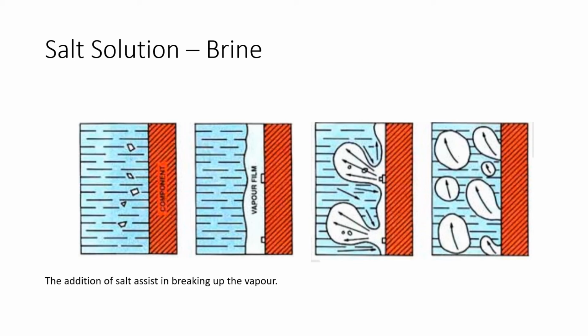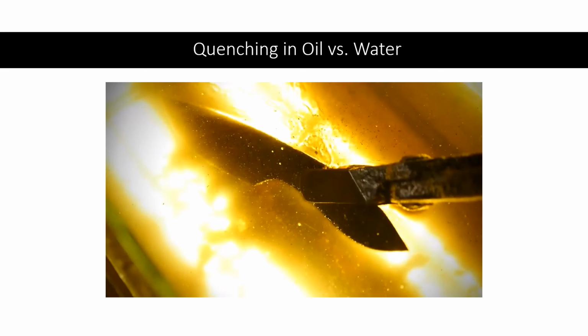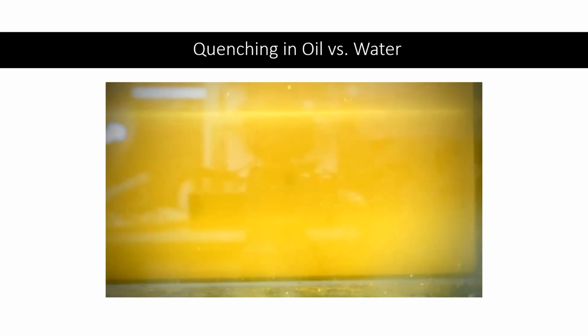This means that a lot more austenite will be transformed to martensite, which is hard in nature compared to ferrite and pearlite microstructure. On the other hand, why does quenching in oil exhibit the slowest cooling rate between the three mediums? The quenching velocity of oil is much lesser than water. This is mainly because the thermal conductivity of water is higher than the thermal conductivity of most oils, and this will result in faster removal of heat from the hot material if it's quenched in water. And this is why water has a better quenching efficiency.